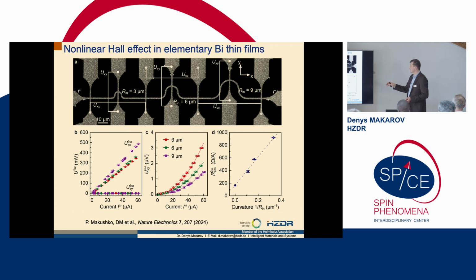And that's exactly one of the ways you can use geometry, a very, very simple way, in order to break the center symmetry of your structure, in order to induce new effects. New effects which are not specific to this material. If you take bismuth, bismuth is a centrosymmetric material. So in principle, any second order effects will simply be forbidden by symmetry in this material. But if you take a bismuth path and you curve it in a semicircle, you will necessarily break symmetry, like central inversion will be broken there. And in this case, you can have, for example, the so-called nonlinear Hall effect. It's a geometric effect which can come on top of something which is happening actually on the surfaces of bismuth, which makes it very, very exciting.